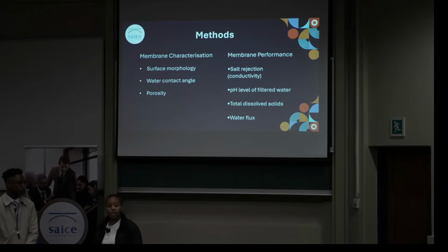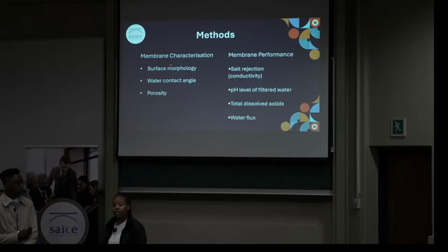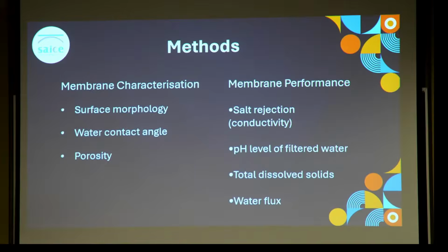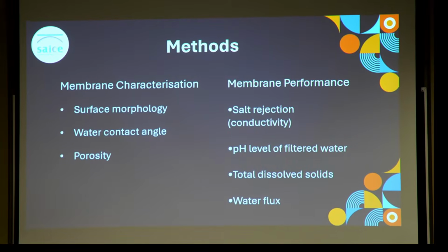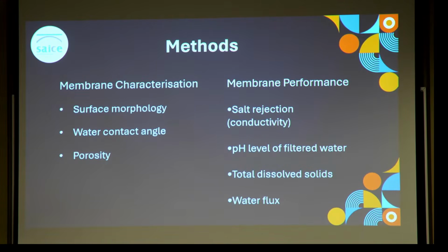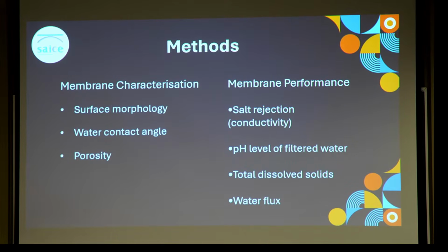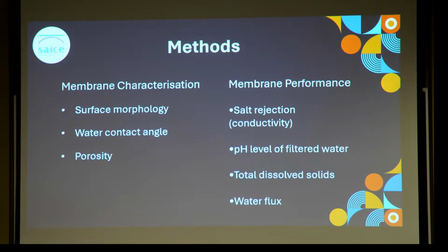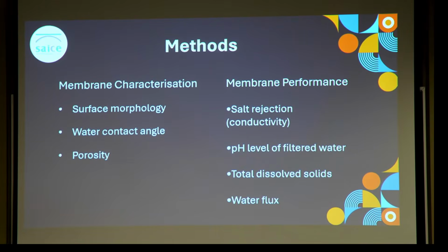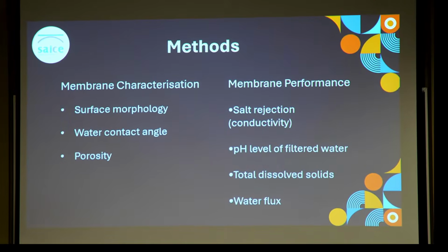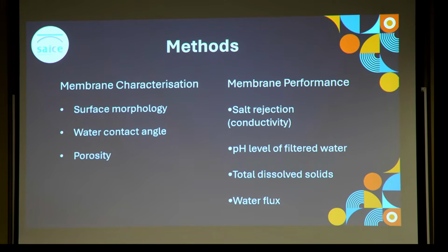To understand how these compositional changes affect the membranes, membrane characterization was carried out. Membrane characterization involves studying the properties and behavior of membranes, which is essential for their efficient application and for determining the most suitable operating conditions in separation processes. For characterization, we measure the water contact angle, which is the angle formed between a water droplet and the membrane surface. This indicates surface hydrophilicity. We also determine the porosity and characterize the membranes in terms of their surface properties. To evaluate membrane performance, the conductivity, total dissolved solids, and the pH of the filtered water was measured, and then the salt rejection and water flux of the membranes was determined.